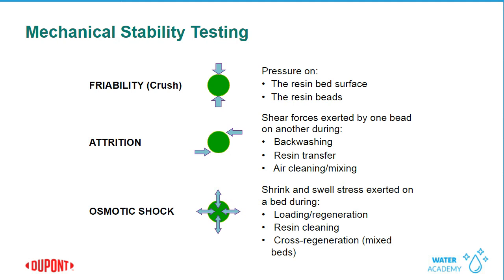We also want to look at the osmotic shock that a resin goes through. As the resin goes through regeneration and service cycle, it can shrink and swell over time and experience these osmotic stressors. Also, if a resin is going to be used in a mixed bed application, it might have the chance of seeing caustic sometimes and then seeing acid if there's any cross regeneration occurring at the interface. So we want to make sure that these resins can hold up in those applications. So we have osmotic shock testing where we're cycling acid and bases multiple times to see how the resin holds up, all to test the mechanical stability properties of each resin to ensure the integrity of these resins for their intended applications.